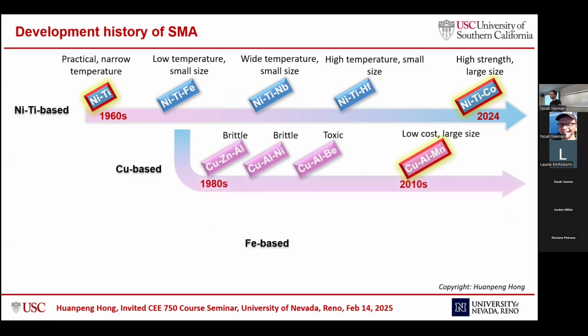And to improve the properties or find a cheaper alternative to nickel titanium alloy, people developed copper-based alloys. The first generation, such as copper zinc aluminum and copper aluminum nickel, are brittle, and later people developed copper aluminum beryllium. These materials behave well, but the beryllium is toxic. And around 2010, the copper aluminum manganese alloy was developed. This alloy has low cost and is available in large size.